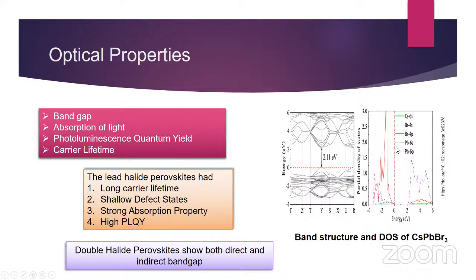And in this diagram, you can see that from the DFT calculation, we can predict the band gap of lead halide perovskite. Here I have shown the band structure of CsPbBr3. You can see a direct band gap with a value of 2.11 electron volt. And here I have shown how the valence band and conduction band of CsPbBr3 are made. This is the partial density of states calculation. Here you can see the 4p orbital of bromine in the valence band and the 6p orbital of lead that makes the conduction band.